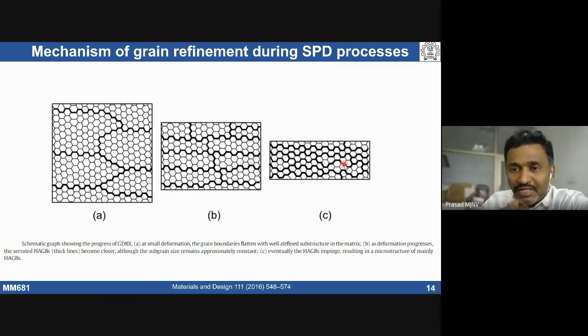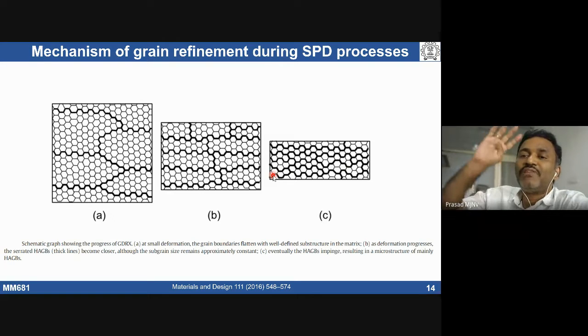So that was the initial CDRX. There was a kind of debate happening about CDRX, geometric dynamic recrystallization. People even used this to explain the grain refinement taking place in the SPD process. So the actual mechanism people have used as a valid explanation is the development of a cell structure, followed by a subgrain structure, and reorientation of the subgrains into a fine grain structure having high angle grain boundaries. If that is to happen, we need to apply a very large amount of strain, like a true strain of 4 to 6.